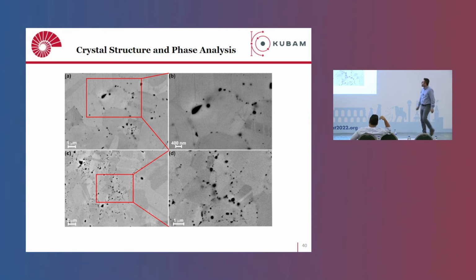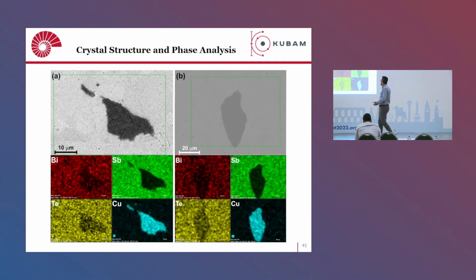Okay, here is the microstructure. You can see nicely that these are the grain boundaries, well oriented, I mean not oriented, but let's say well-resolved grain boundaries. And at the grain boundaries, we see mostly copper telluride. The copper telluride that we introduced is mostly decorating the grain boundaries. So this is good because this is a metallic material, which might help with the electronic conductivity, but at the same time, it is a secondary phase, which can lower the thermal conductivity.